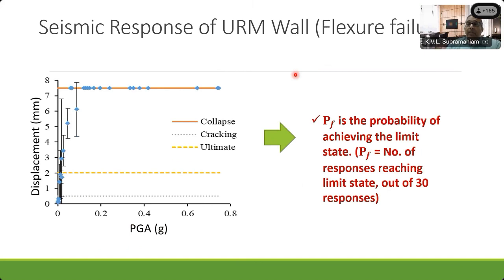Now, what about a wall that fails in flexure? This is a wall which has an aspect ratio which is greater than 1, say 1.5, and has a moderate amount of compression. Same story repeats itself. So you see that even the flexural wall would crack at a very small value of PGA. It would even reach the capacity, the strength limit at a low PGA. And by about 0.1 or so, you'd start seeing collapse of those walls as well.